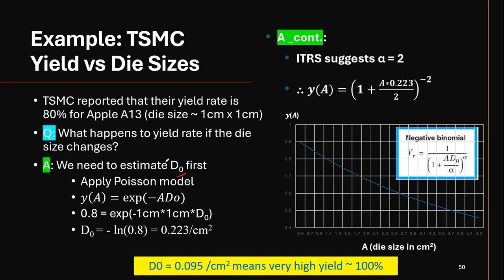So this one, I'm going to take it at D-naught first. I use a Poisson model. Poisson model yield is exponential of negative area times D-naught. And D-naught is 0.2 per centimeter squared. And then this is the negative binomial distribution suggested by ITRS. So if you have 80% yield when the die size is 1, then this is what it should look like. The larger the die size, the smaller the yield. Right.